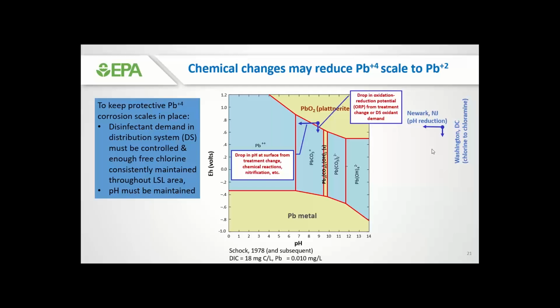So if we go back to the Pourbaix diagram and let's assume we're at the good passive state of having formed lead +4 oxide, or plattnerite, at the top right of the diagram, any change in drinking water quality that will make us shift to the left of that diagram, or from top to bottom of that diagram, will make us move from the beige area to the light blue area here. So it's really important to make sure that that doesn't happen. And of course, changes do happen in drinking water systems, and it is possible for those protected pipe scales to be destabilized. For example, in Washington, D.C., we had a case where a change in disinfectant from chlorine to chloramine caused a drop in the oxidation reduction potential. So we had a vertical shift on the y-axis on this graph, whereas Newark, New Jersey was a situation where a drop in pH actually destabilized the previously formed lead +4 scale.